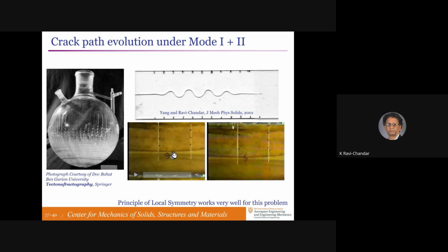It's about 1 inch wide by about 5 inches long or so. Heat them up to a certain temperature, and then dip them in cold water. So it's the inverse of this. It's heated up, and then you dip it in cold water at the same rate. It dips into the water, forms a meniscus, and then a crack you can see is leading up there, and it's leading up here from this point. The only difference between these two specimens is the temperature change. The left one has 105-degree temperature change, the right one.